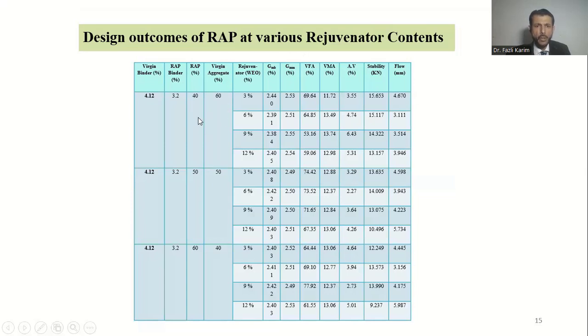So recycled mixtures were prepared containing 40% RAP, 50% RAP, and 60% RAP. These quantities were selected with the intention that the RAP quantity in Pakistan can be expanded. Similarly, all the volumetrics were calculated. But as you know, for aged asphalt, some rejuvenators are required so that it may complete the percentage of saturates, aromatics, resins, and asphaltenes. So using these recycled mixtures and rejuvenator, all the volumetrics were calculated.